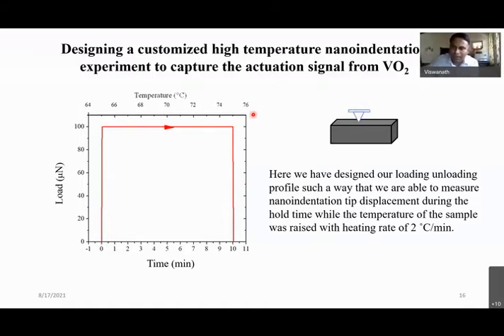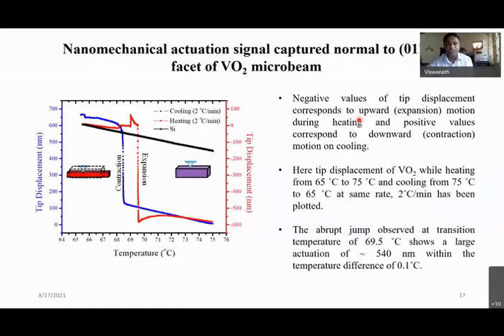In principle, if the sample is expanding, the expansion should push the tip up. If the sample is undergoing a contraction or shrinkage, the tip essentially should be pulled down. For a constant load, how the tip can be displaced by the expansion or contraction of the crystal during the phase transformation, that is what we are interested in probing. I'm showing here the result, tip displacement as a function of temperature.